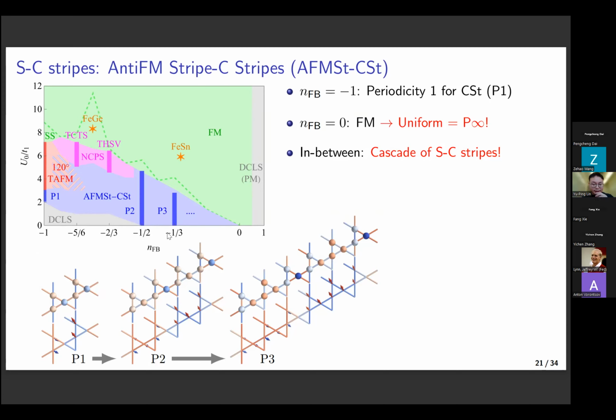And if we look at the -1/3 filling of the flatband, we can see that the charge stripe periodicity is tripled, and also the AFM periodicity. So we are seeing a very elegant spin and charge stripe cascade of periodicity for a filling of -1/n. And the very good intuition for this is that as we are increasing the filling from -1 to 0, we're gradually filling the lower density stripes.